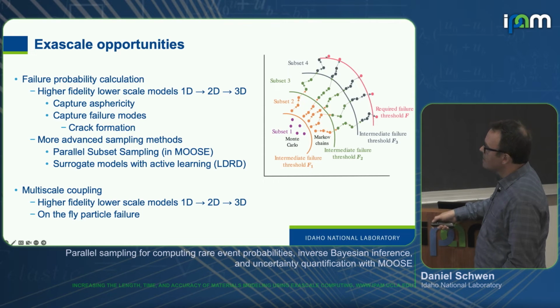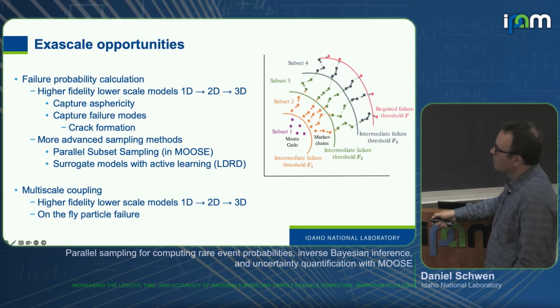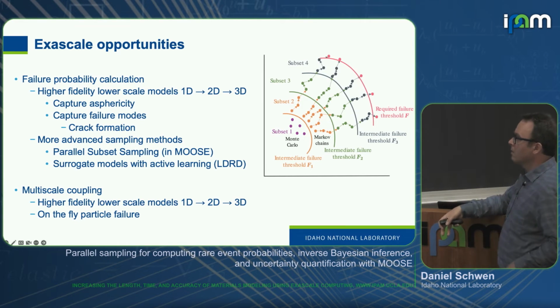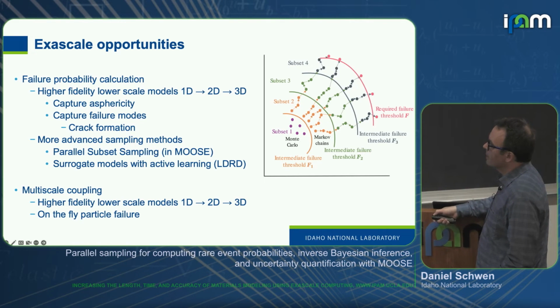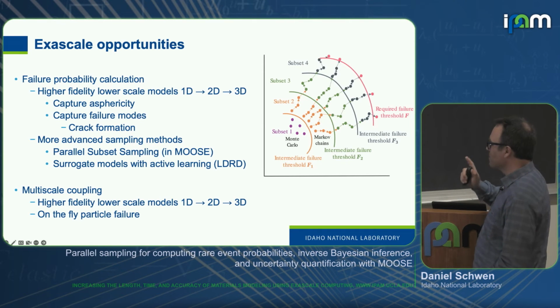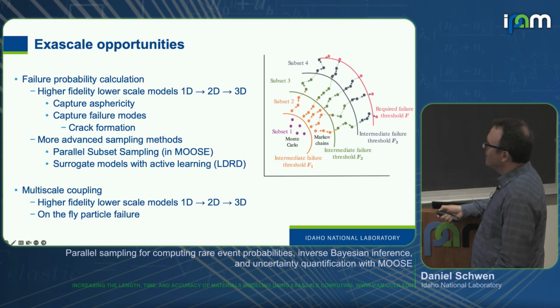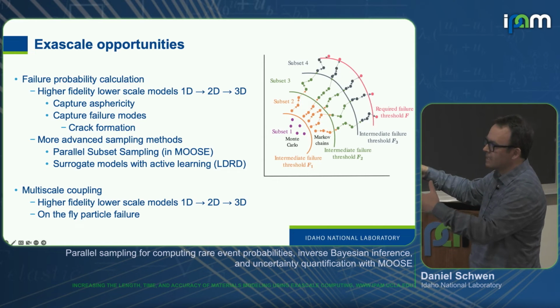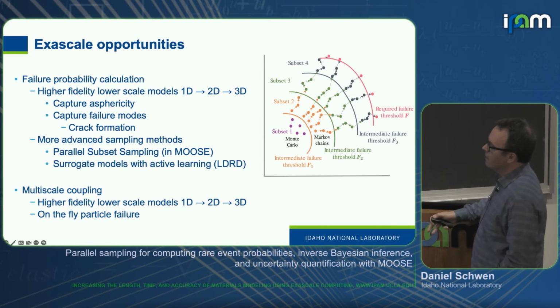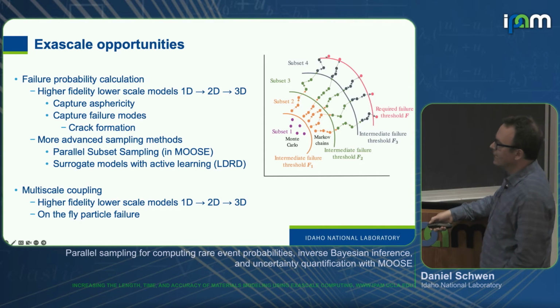So there are definitely exascale opportunities here for the failure probability distribution. If we have more CPU power, we can easily use that to have our lower scale models not just one-dimensional, but two-dimensional, three-dimensional, which would enable us to discover and capture more failure mechanisms, such as properly capturing asphericity and crack formation. We do already have a more advanced sampling method than just Metropolis Monte Carlo. We have parallel subset sampling, where we automatically detect intermediate failure thresholds and only propagate Markov chains that advance us towards a failure threshold, and that can radically reduce the number of samples needed.